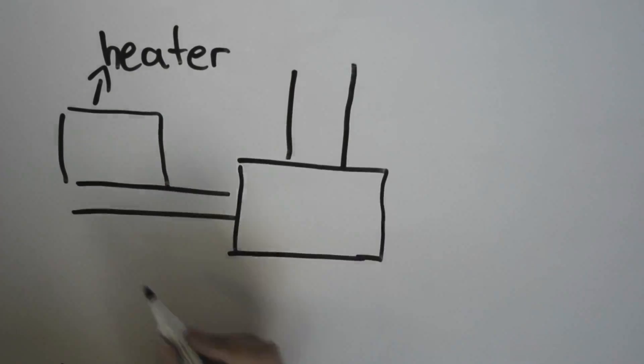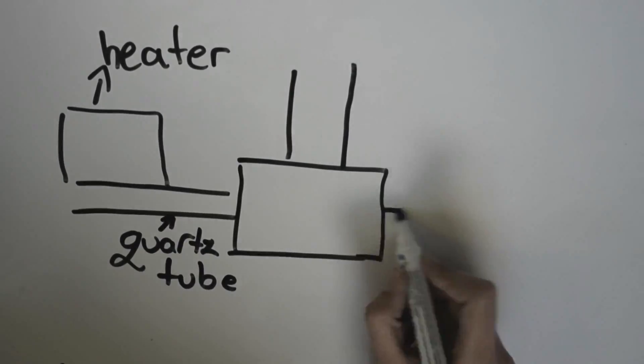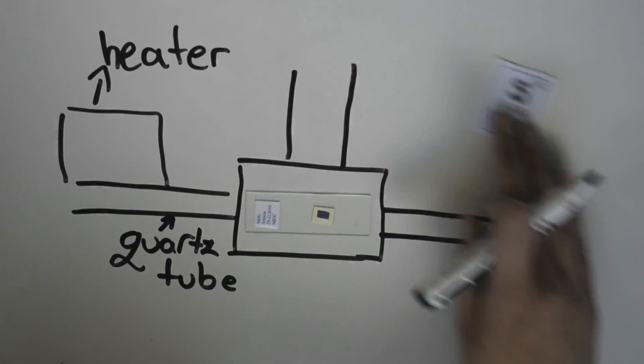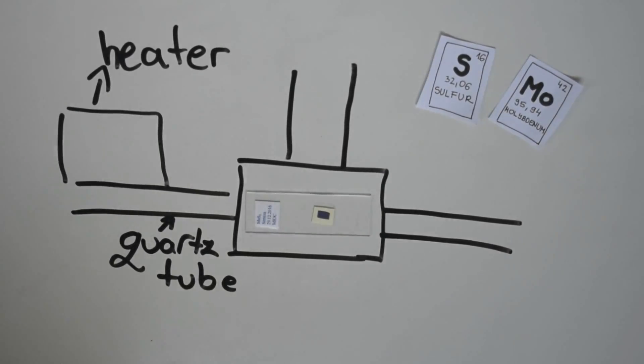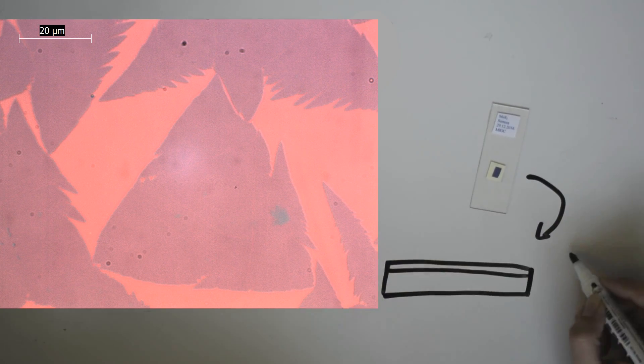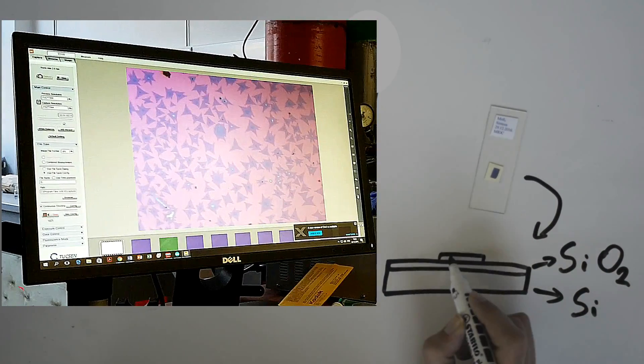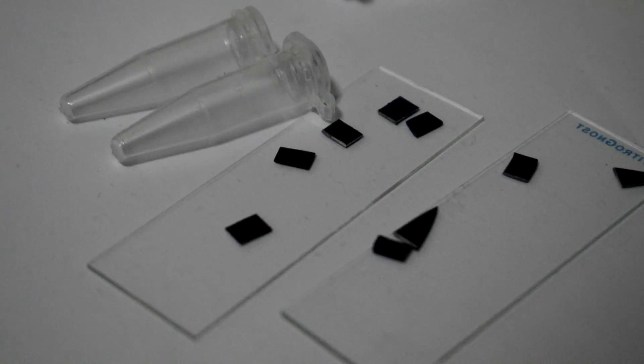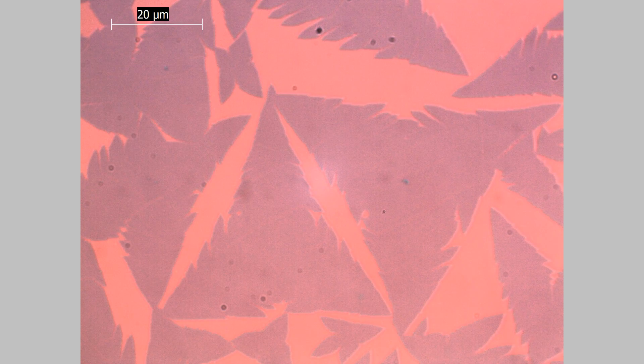At the Institute of Physics, we have synthesized MoS2 with a technique called chemical vapor deposition. Following a special recipe, meaning under a particular pressure, temperature, and amount of atoms, we use argon to bring sulfur and molybdenum. The crystals are synthesized on a surface made of silicon and SiO2. The result of the crystal growth are MoS2 monocrystals in a triangular shape.